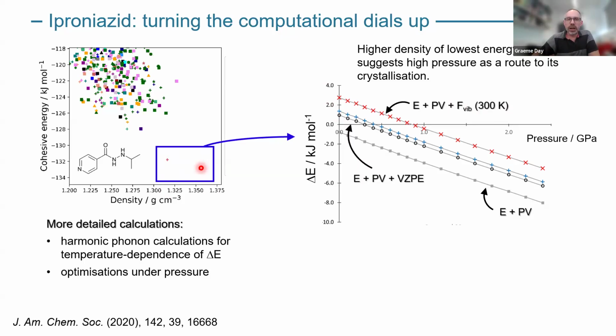But we weren't satisfied with that. Still, this structure looks low in energy. And something we notice about it is it's higher density than the observed structure. So something we thought about trying was pressure. So we can do this computationally very easily. We apply pressure and recalculate the relative energies. And now we can do this at room temperature. So we've calculated the vibrations of atoms in our molecule, in our crystal structures. And we find that if you get to pressures of 1 gigapascal, then the order swaps back. So now this unobserved structure at high pressures is the lowest energy structure.